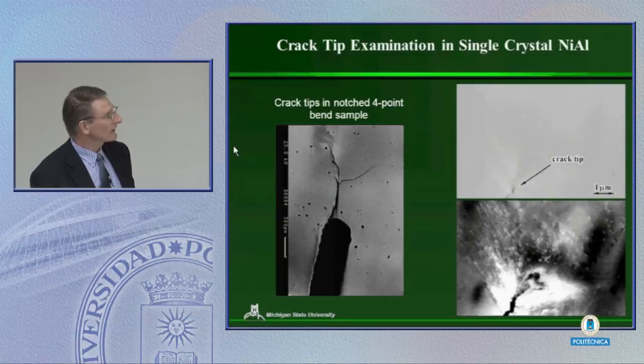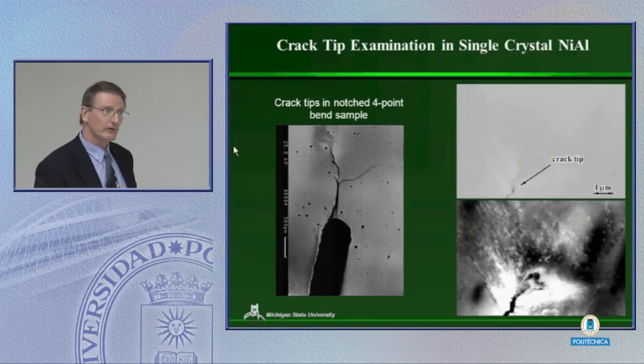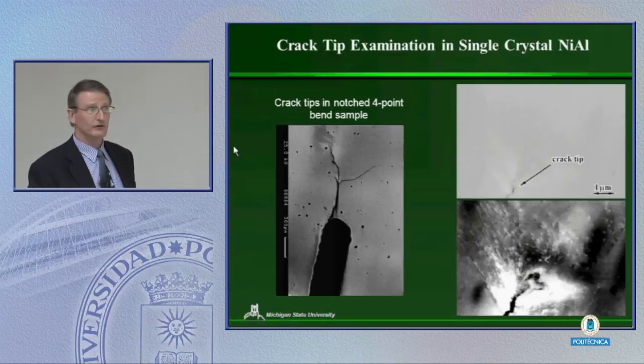Here's a secondary electron image of that crack tip. But now when we actually look at the crack tip with channeling conditions, we can see the individual dislocations out in front of the crack tip. So we can measure the extent of the plastic zone. Certainly as we get closer to the crack tip, the number of dislocations increases dramatically. That is partly the reason we get all this blooming here.